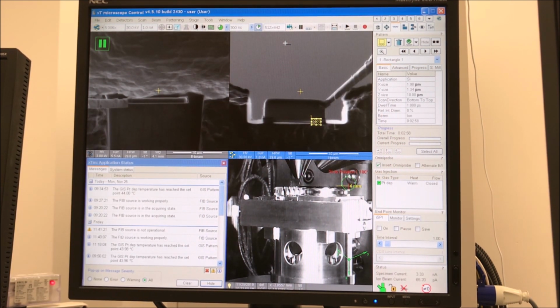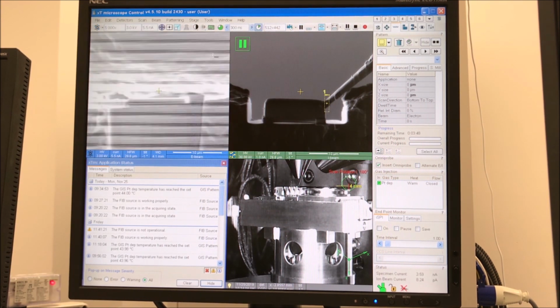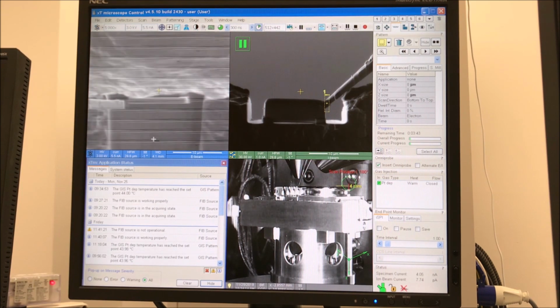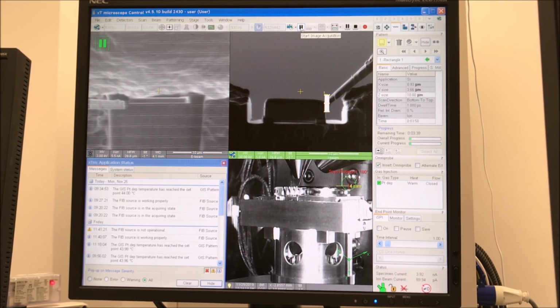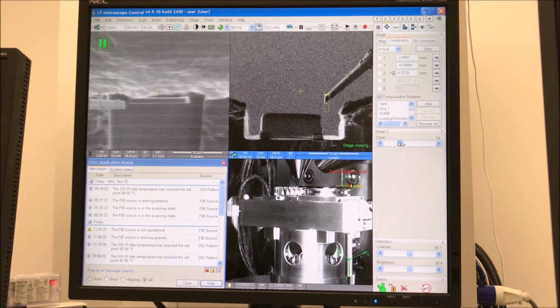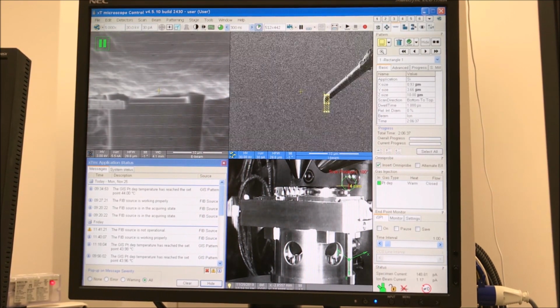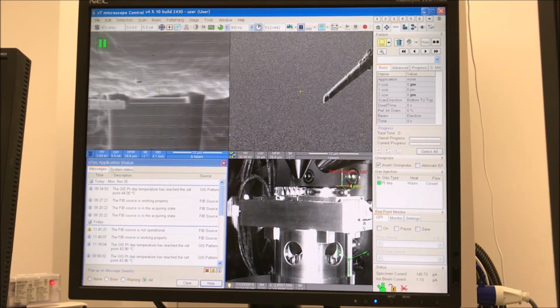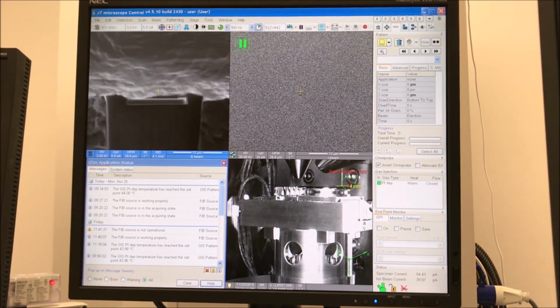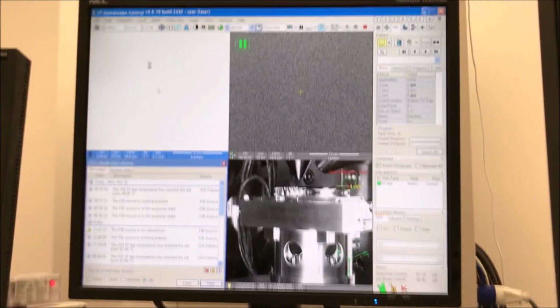Okay, so we have our welds done, and now we need to cut the omniprobe free. So I changed my pattern to silicon and my ion beam current to 1 nanoamp, and I just positioned it over the edge of the omniprobe and executed the pattern. And I can see now my omniprobe is free. Then I moved back to 30 picoamps. I again separated the lamella from the omniprobe by moving the stage down, and then I can remove the omniprobe and the platinum GIS. So we're getting now to doing the final thinning.